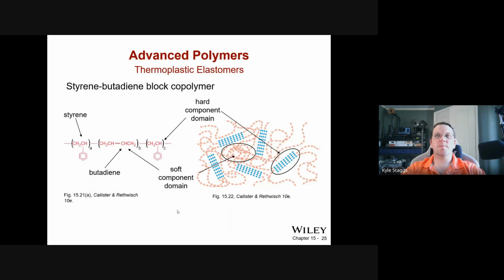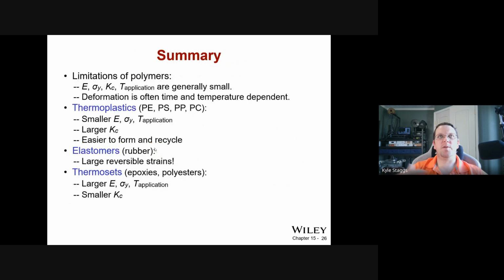Advanced polymers typically combine hard component domains, something like block polymers, with shock absorbing or soft compliant domains, with different regions by changing the ratios of those. Styrene butadiene is a good example. Styrene has a benzene ring, very inflexible. Butadiene has just a double bond, so a little bit of flex, but not much. And then very inflexible in the case of the styrene when it's highly polymerized. Those are all examples of things that we want to be able to tune for different kinds of properties.